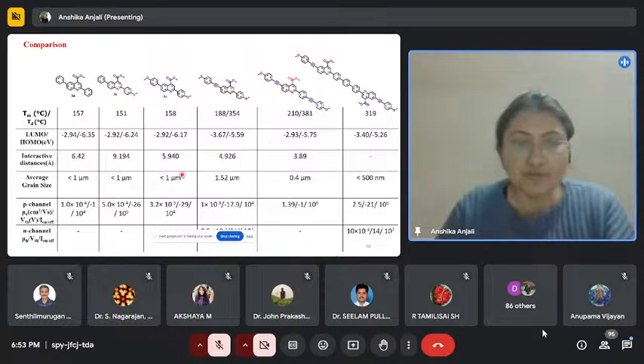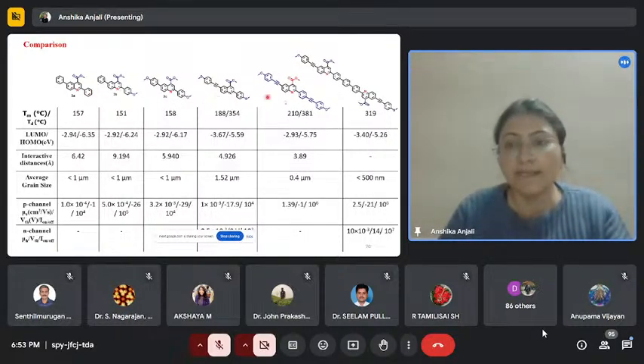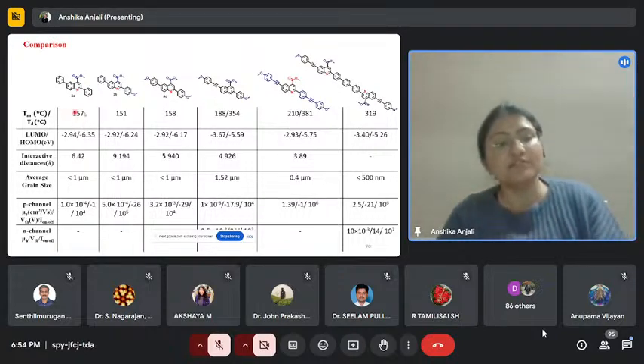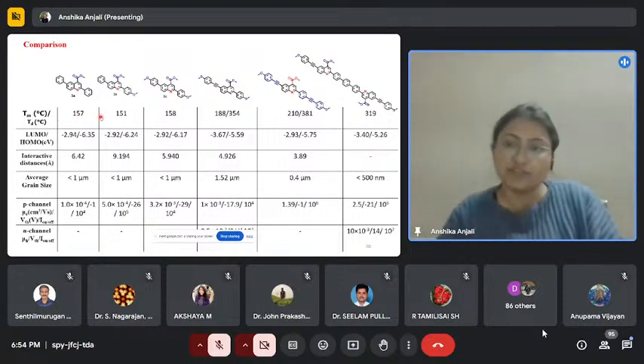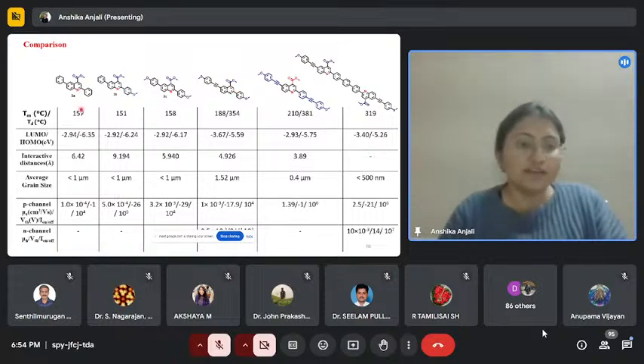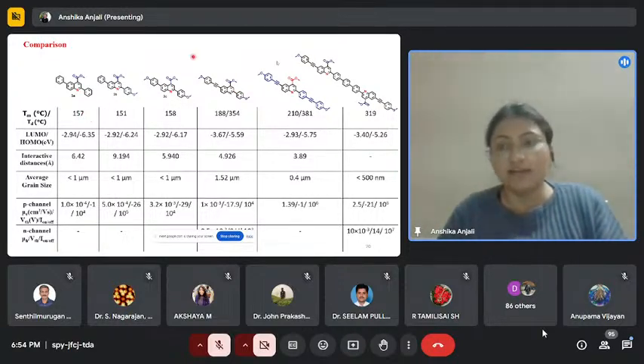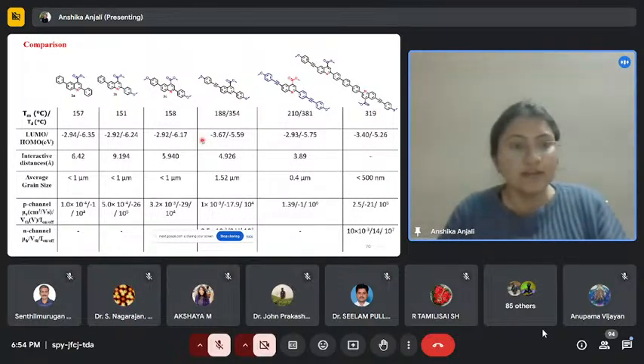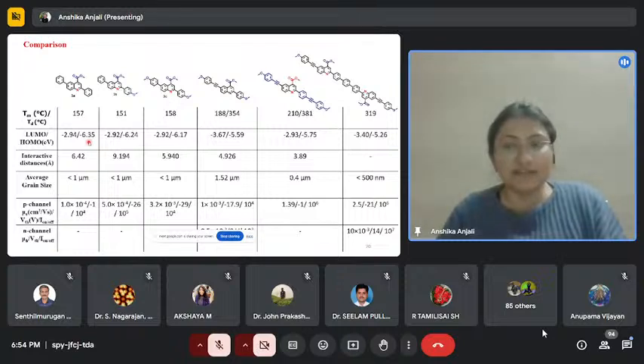So to give an overall summary, with the extension in conjugation and introduction of linkers, we have seen that for these compounds, their melting point and decomposition temperature were increased. When we started, compound 3A had a melting point of 157 degrees, and the later one has a decomposition temperature of 319 degrees Celsius. We have also seen that their HOMO and LUMO energy levels were increased. The interaction distance values were calculated.